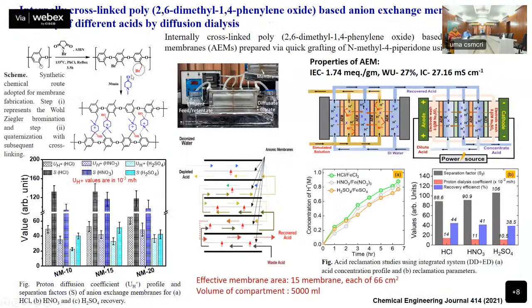We have also another type of membrane which is prepared from polyphenylene oxide. It was first brominated and then quaternized with N-methyl-4-piperidone. This membrane was used for the recovery of acid from metal salt mixture by diffusion dialysis. This is a spacer-free membrane, and it is prepared by the solution casting method. Once the acid is recovered by the diffusion dialysis process, it can be concentrated by electrodialysis. And this membrane is useful to separate HCl, nitric acid, and sulfuric acid from their metal salt mixture.